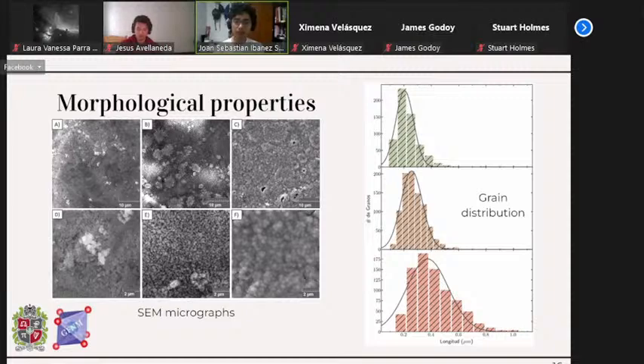With the images we took at 20,000 magnification, we obtained the grain sizes for each of the sintering processes and found the histograms on the right, in order of ascending temperature from top to bottom. In particular, you can see that the first one, the green one, which is the sintering process for the 850 degrees Celsius, had a grain size smaller than for the last sintering process, the red histogram, in which the grain was noticeably larger.